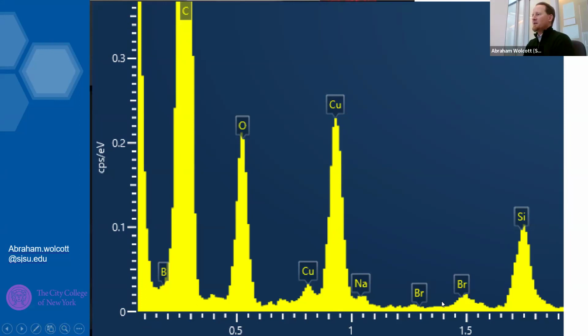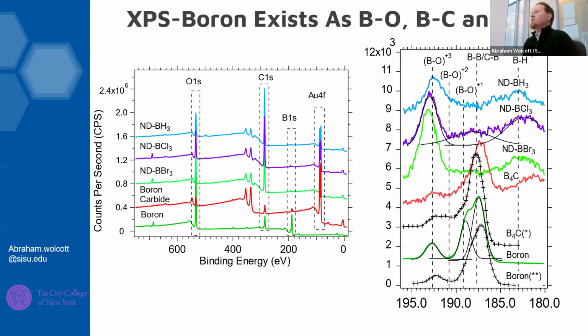You'll notice, though, that we do have some information from the bromine. So some of these bromines remain on the surface of the diamond. You would think that they're still bound to the boron, but we don't quite know that. If we use XPS, we can do survey scans, which you can see on the left-hand side. I've got a number of control samples, boron carbide and boron, but all of the action is right here. This is our core level B 1s emission.